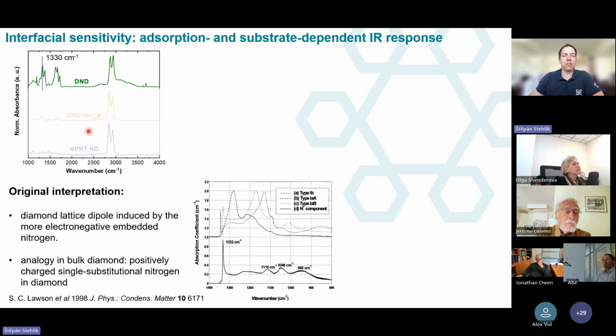And we always, up to now, assigned this peak to the embedded nitrogen, but in a kind of physical way: the embedded nitrogen, because of its higher electronegativity than carbon, can induce some dipole moment in the diamond lattice, and that's why suddenly it's visible for the IR radiation. We also had a nice analogy, a nice paper to cite in this regard. It is this paper of Lawson, where they showed the appearance of this Raman-like peak in nitrogen-doped diamond, and they assigned the appearance of this to single substitutional nitrogen after positive charging. So we always thought that we have this peak because of the nitrogen and some similar effect.